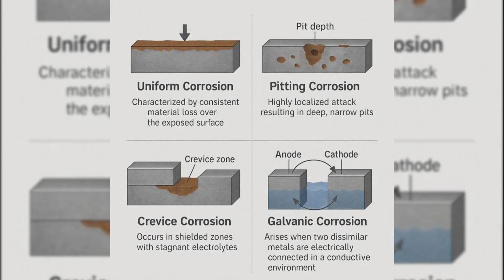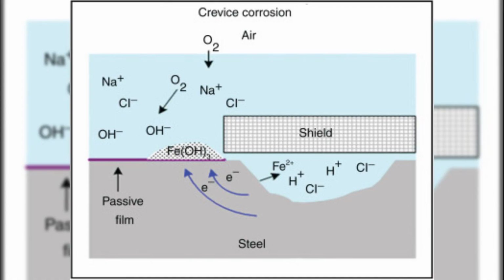Closely related is crevice corrosion. This form develops in narrow gaps, under gaskets, bolts, lap joints, washers, or overlapping plates. Inside these crevices, oxygen becomes depleted, while ion concentration increases. This creates a strong electrochemical imbalance between the crevice interior and the surrounding surface. The result is intense, highly localized corrosion that remains hidden until structural damage is severe.